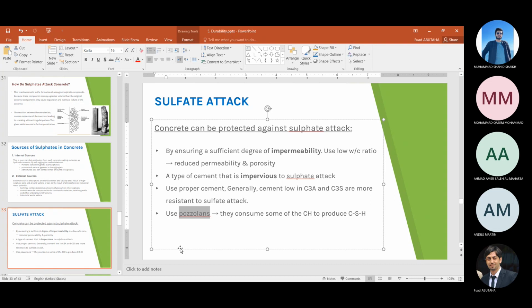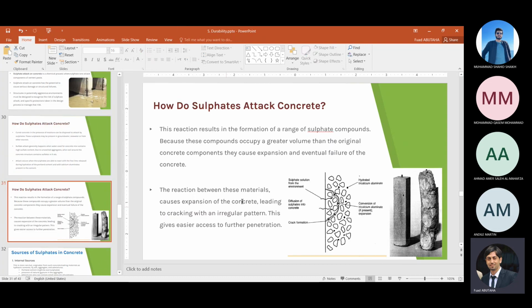Filler material, mineral admixture. This one will contribute when it consumes the calcium hydroxide and converts it to calcium silicate hydrate, and it can also contribute by its filling ability or filling capability to fill all the spaces inside the cement matrix or cement paste. And this is how the sulfate attack results in concrete deterioration and failure of the structure.